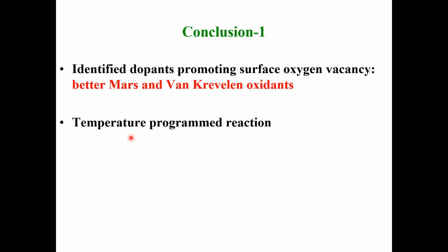So how do you envisage this experiment? First I do this experiment with zinc oxide, and I calibrate at what temperature oxygen is evolved from this undoped system. Then I do the same experiment with the dopants to get at what temperature oxygen comes out, and you compare your experiments with the computational screening that I mentioned before.